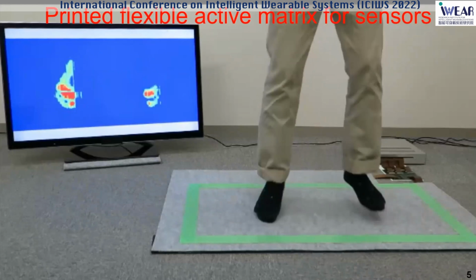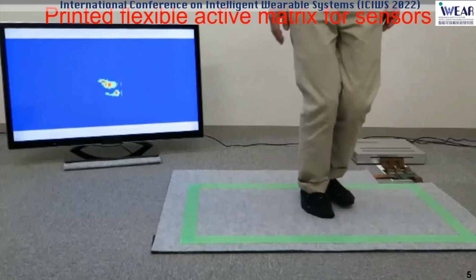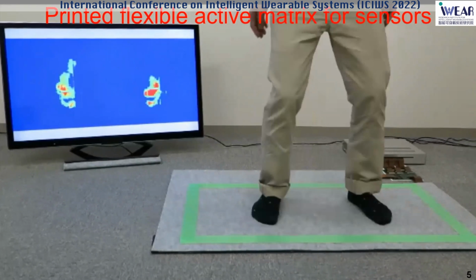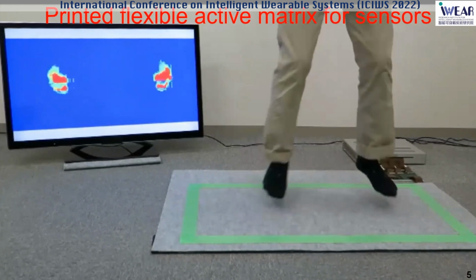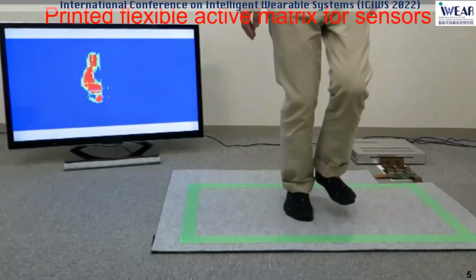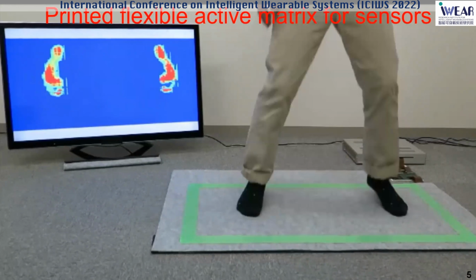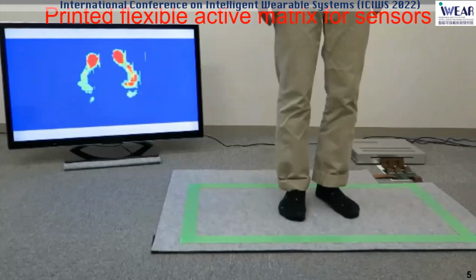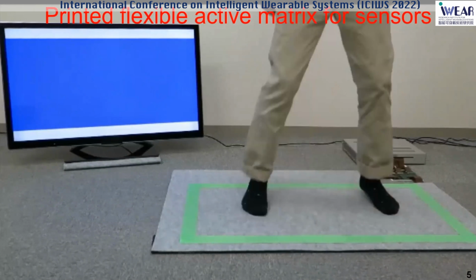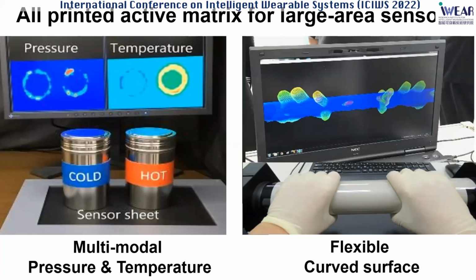And then this movie shows you how our device works. It doesn't look like a flexible device, but if it were manufactured on a glass substrate, this kind of jumping motion may cause fatal device failure. But because it's manufactured on mechanically durable plastic foils, it can achieve high spatial resolution and high data readout simultaneously. And also we can monitor the pressure distribution and the temperature distribution simultaneously. Because of the mechanical flexibility, our e-skin can be wrapped around a cylindrical bar, and then we can monitor the grip pressure in this three-dimensional configuration.